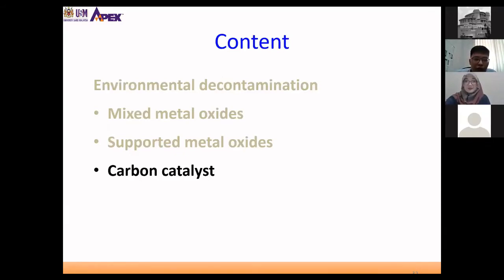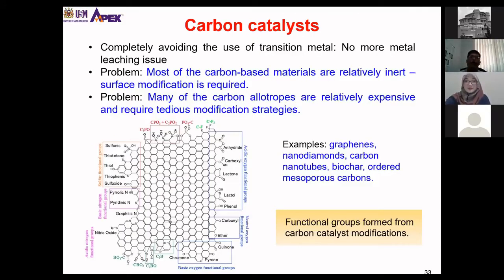I want to introduce to you carbon catalyst. Carbon catalyst is one of the hot fields today. So I am working a lot on carbon catalyst today. And yeah, carbon catalyst itself completely avoids the use of transition metal, which means you don't have to worry about iron leaching, metal leaching, cobalt leaching, copper leaching. Anything that has no metal will not have any metal leaching issues. But then, of course, carbon catalyst has its own problem. The thing is that it's relatively inert in the sense that you need to modify the surface by introducing surface defects and certain functional groups that can be used to activate the oxidants.